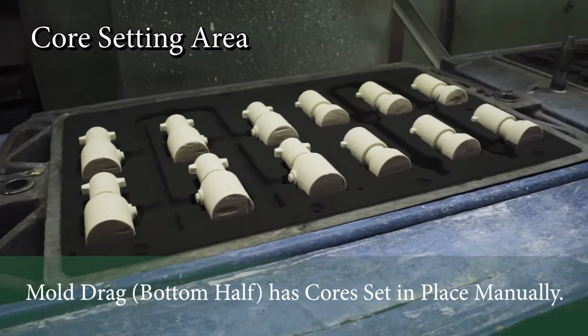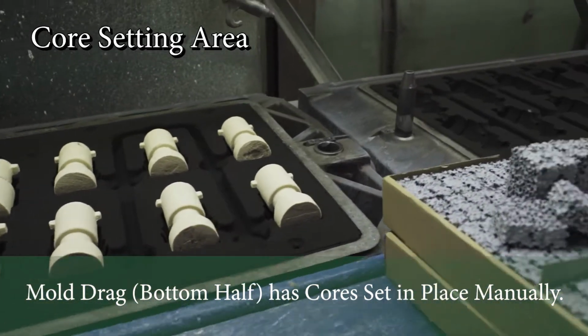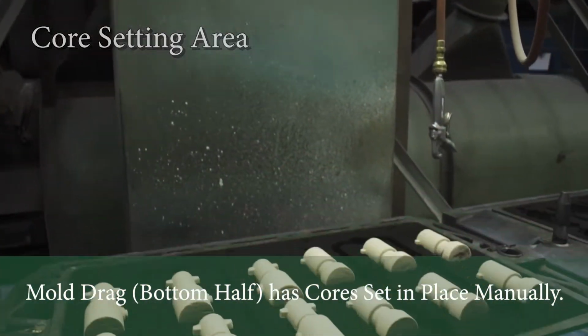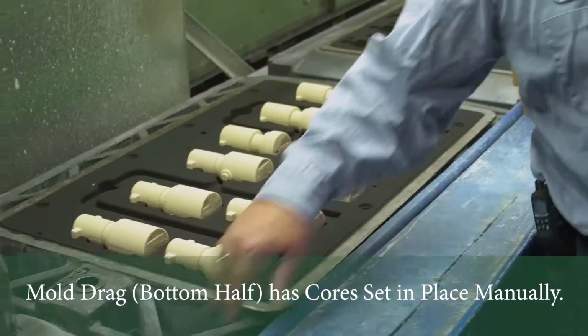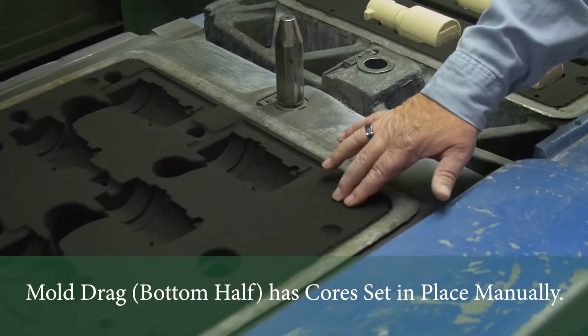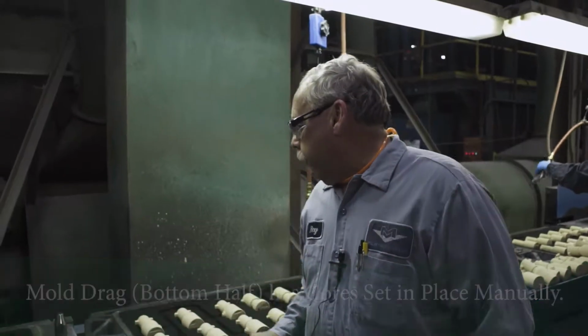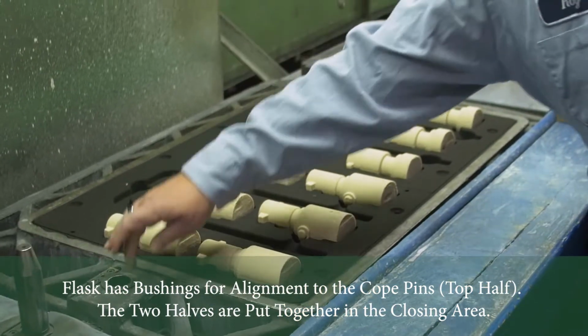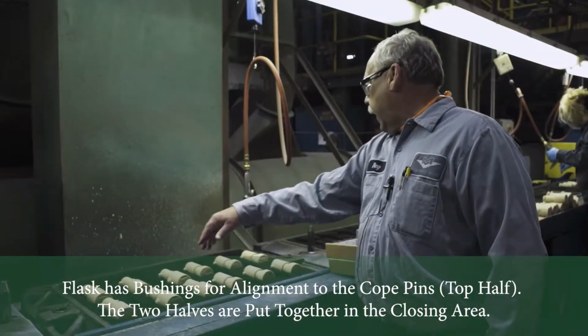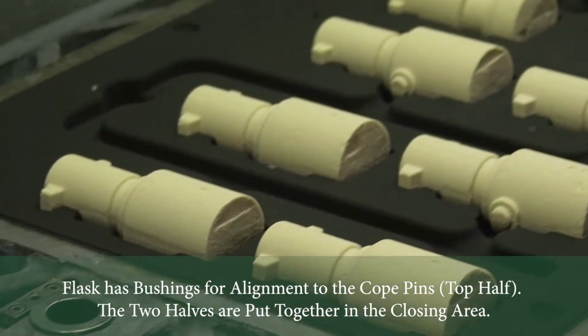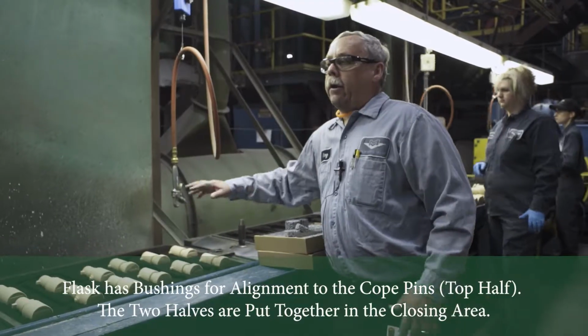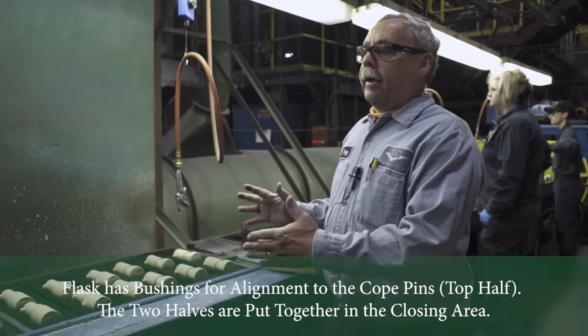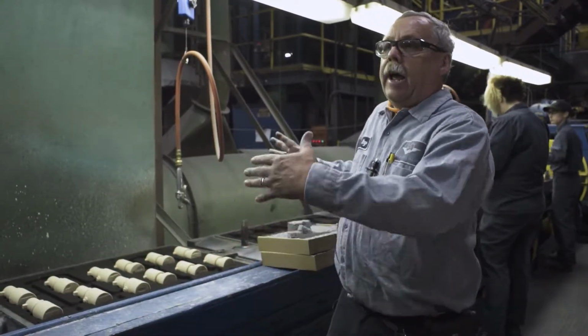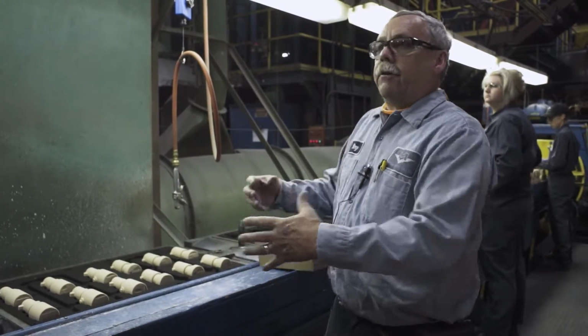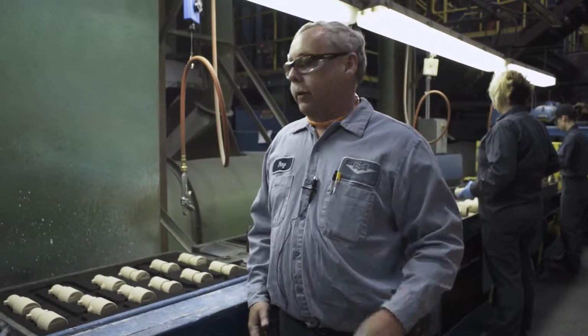Okay, this is our closing line. The cores, as I talked about earlier, are set to the bottom half of the mold, which is the drag. This sand is very hard. It has a mold hardness of about 92 to 94. And it has a round opening and a round pin that makes the alignment when we put these two halves together. The round pin goes there, and then we've got a square pin that fits in elongated holes to allow for expansion as the pattern and the sand heats up during the day, so we have to allow for inline expansion.